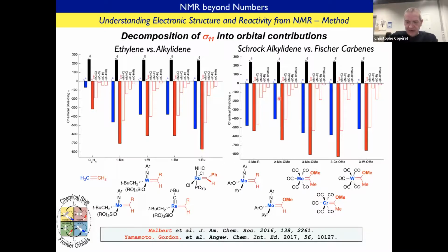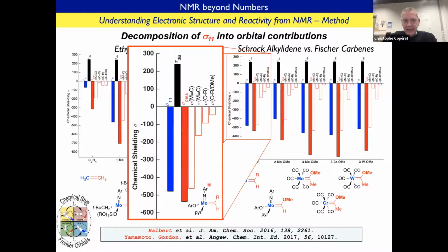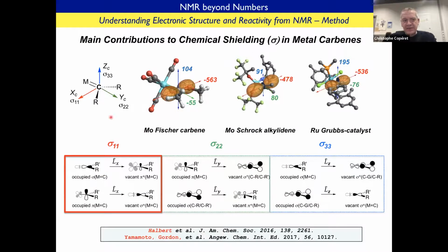site. But more importantly, if you look more closely at this Schrock alkylidene, you can see that the dominating factor that leads to a very large chemical shift value is the metal carbon bond, and in second term, the pi bond of the metal carbon. We can try to understand why this metal carbon bond is so important in driving the chemical shift in this compound. In fact, purely by symmetry, since you know that this chemical shift component is perpendicular to the MC frame, and that the metal carbon bond is a driver of the chemical shift, what you can identify is that there must be a low-lying pi star orbital close in energy to the sigma bond to drive this chemical shift. That's what this analysis can do.